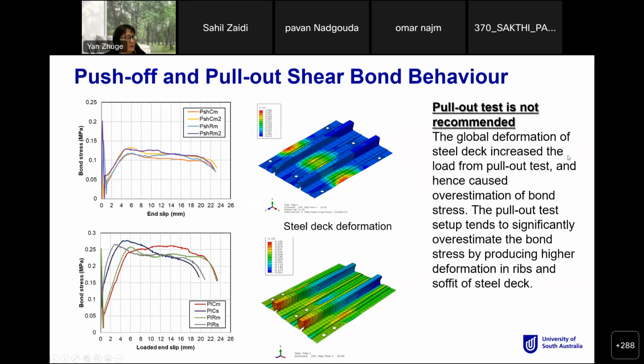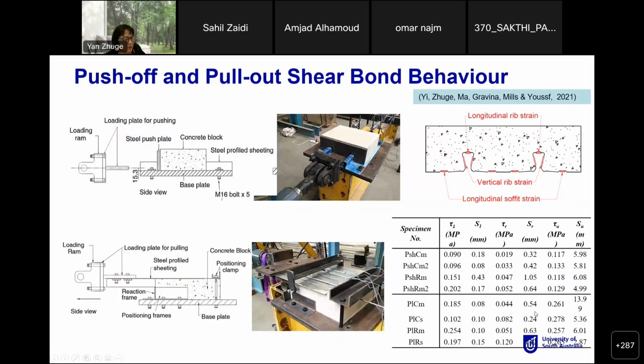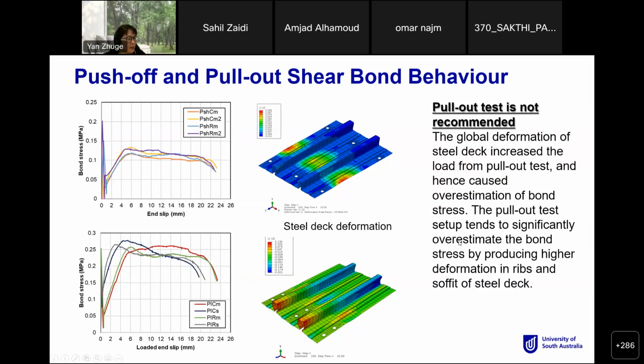So we find out the pull-out test is not really recommended for further applications because the global deformation of the steel deck increased the load from the pull-out test and hence caused the overestimation of the bond stress. So that's why they got some very high bond stress results compared to the other one. So you got some high there. And the pull-out test setup tends to significantly overestimate the bond stress by producing higher deformation in the ribs and also the softness of the steel deck. So therefore, if you want to perform small scale composite testing, we recommend using the push-off but not the pull-out test. Okay.